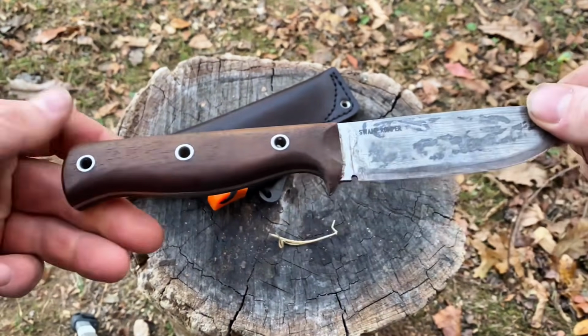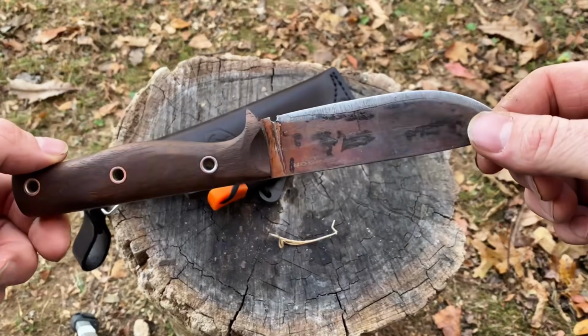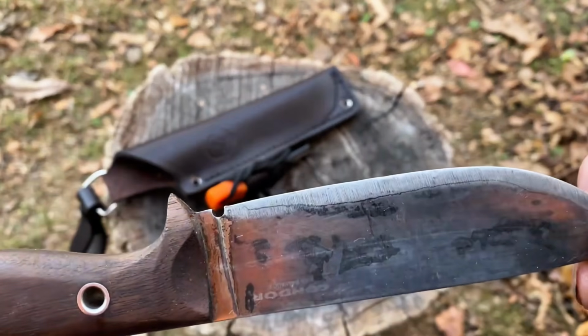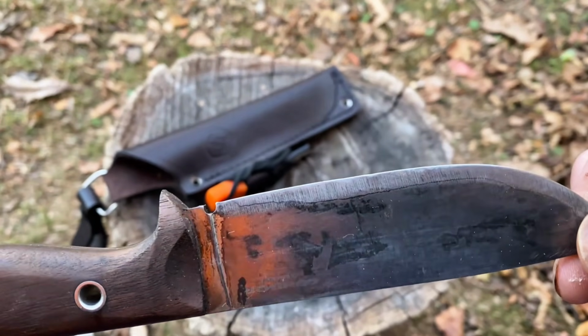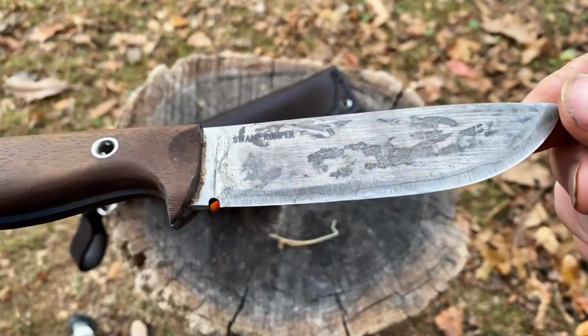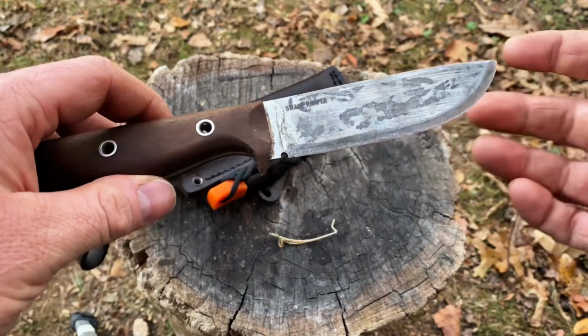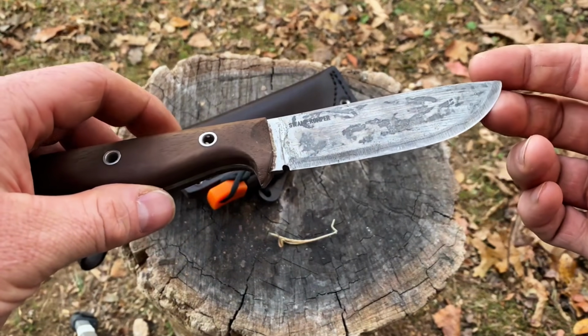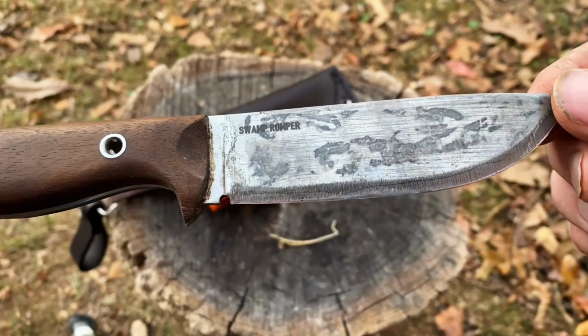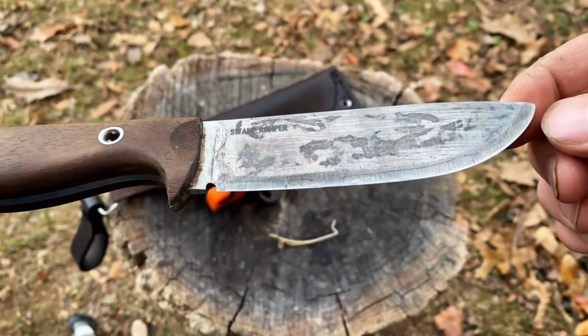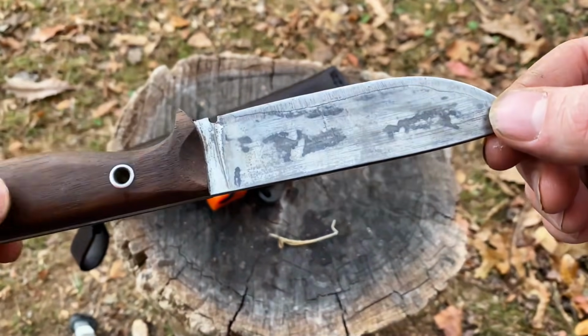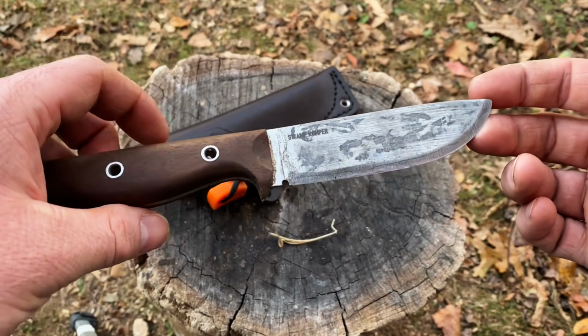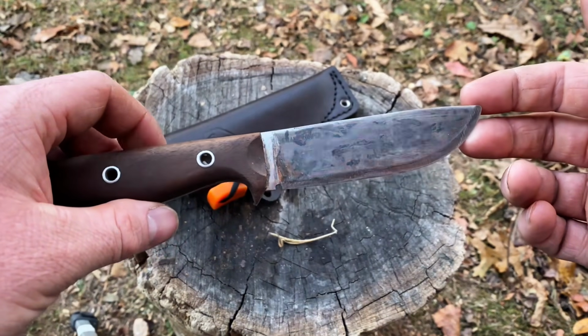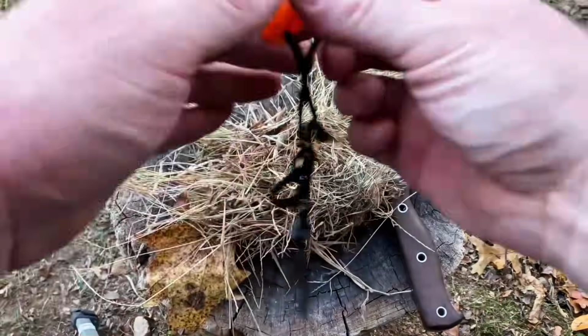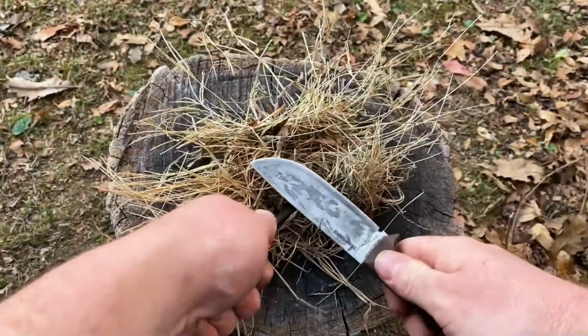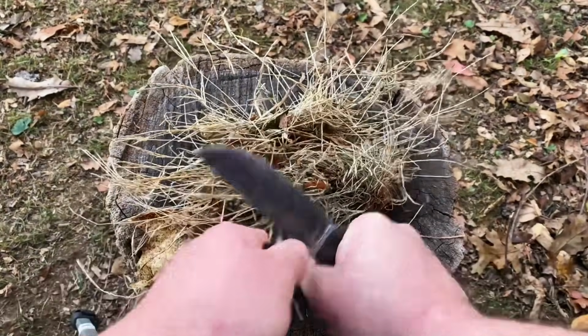In the chopping and battening sections, the Swamp Romper cleared more material faster than any other knife in this evaluation. The convex grind acts like a wedge, pushing material apart rather than slicing through it, and the 1075 steel at 57 to 59 Rockwell provides the toughness to absorb the impact forces that chopping generates without edge damage. If the test had stopped at battening and chopping, the Swamp Romper would be in the passing category without discussion. The failures appeared in the secondary tests.